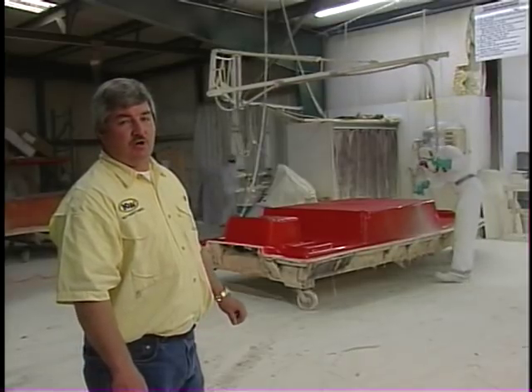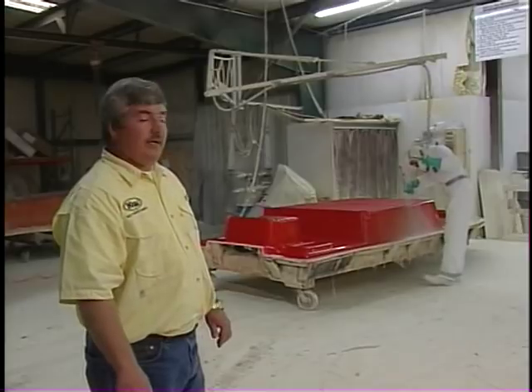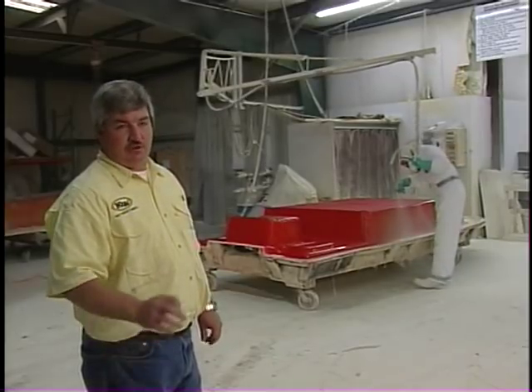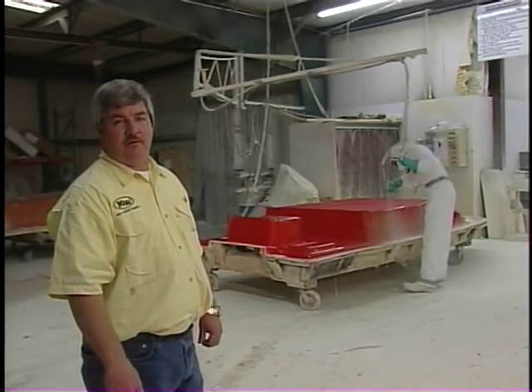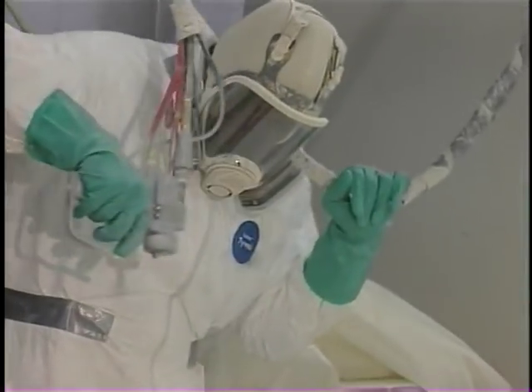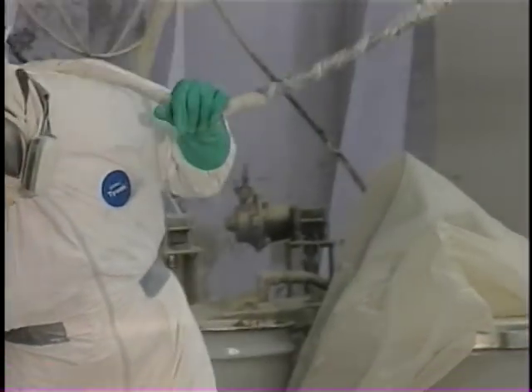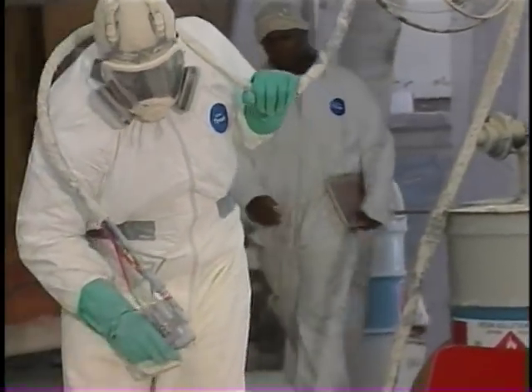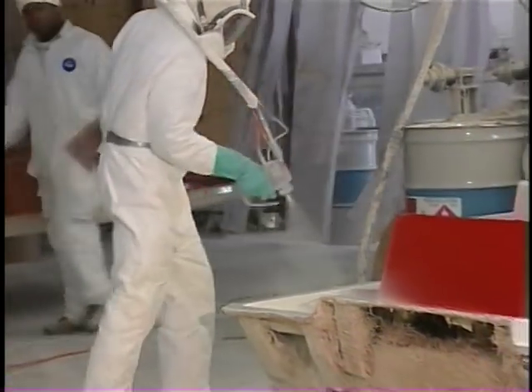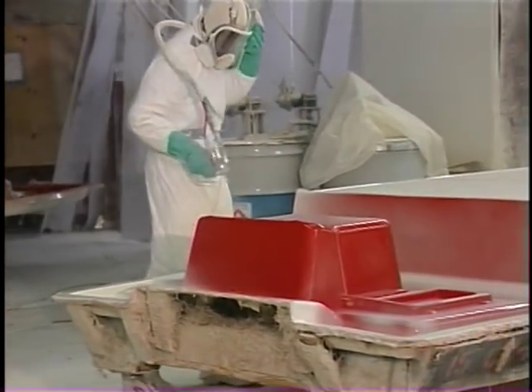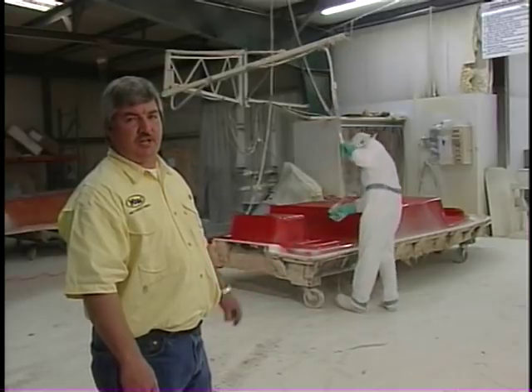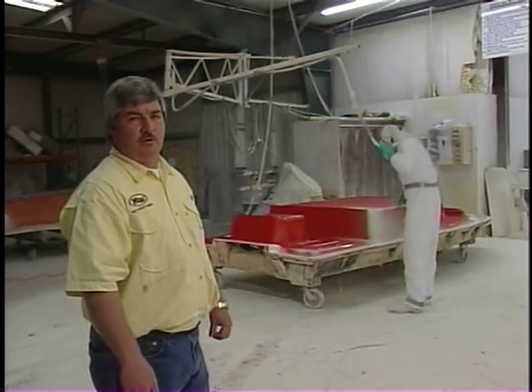And he's putting this gel coat on, and he's got to apply it at the exact right mil thickness to make sure that we'll get the proper weathering of the boat. If it's too thin, you'll get alligatoring. The gel coat will wear out. You won't have the waterproofing. If you get it too thick, you'll have stress cracking and problems with weathering later too. So this is the most important step, to make sure that the gel coat is put on at the right thickness.